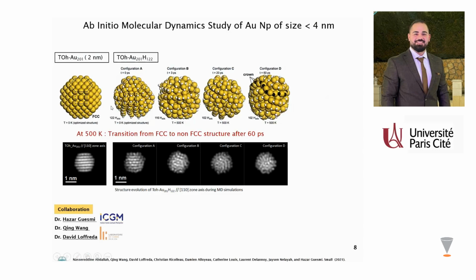structure in vacuum, and even when covered by hydrogen at 0 K. The morphology completely changed after 60 picoseconds of molecular dynamics, to obtain a rounded morphology and a different crystalline structure. This structural transition has also been confirmed by STEM modeling of each molecular dynamics structure obtained during the modeling.